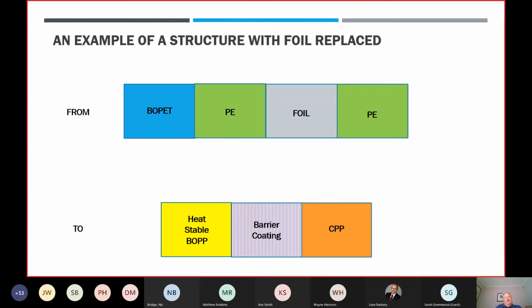And here's an option, and it's an option that I'm currently looking at with a major global player, and that's to replace the BOPET with a heat stable BOPP, include a barrier coating that gives performance close to foil, and then replace the PE on the inside with cast polypropylene. So what you actually have in that structure is 99% polypropylene and a little bit of barrier coating, probably about 1 gram per square meter, that doesn't inhibit the ability to recycle that product.